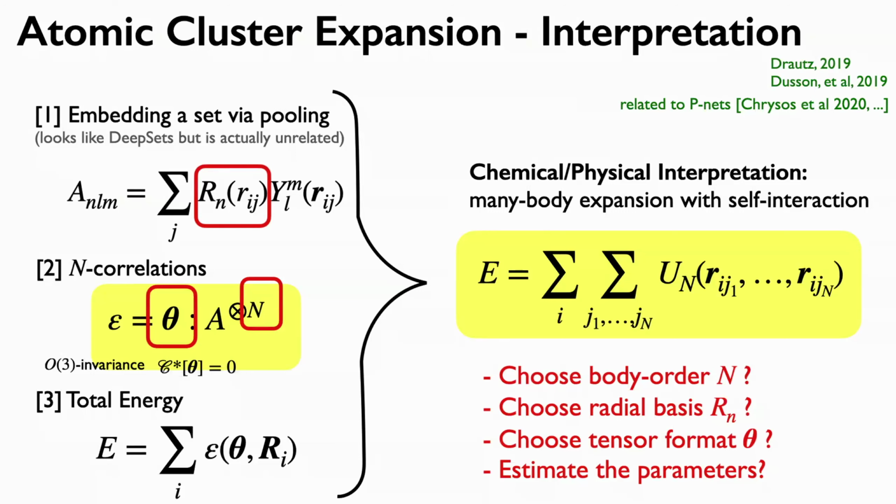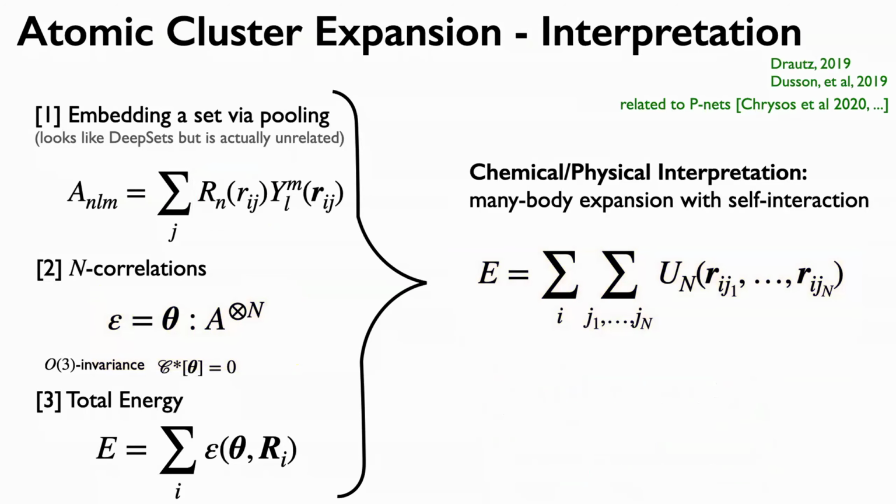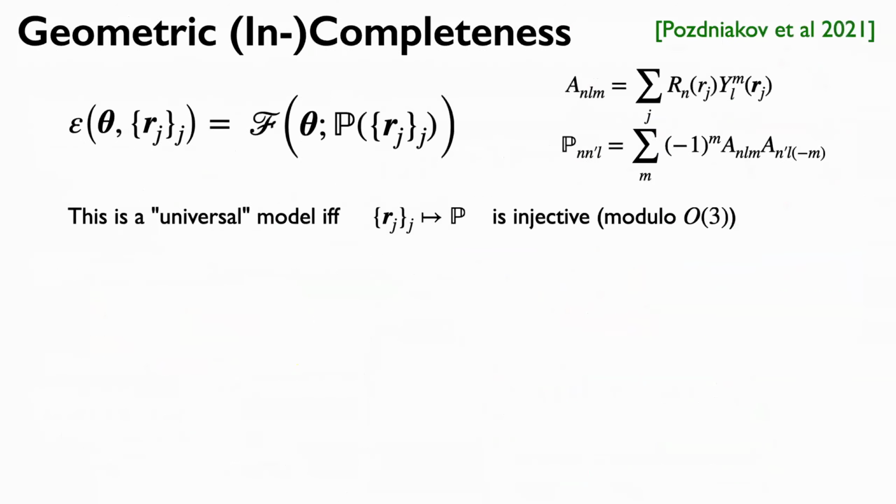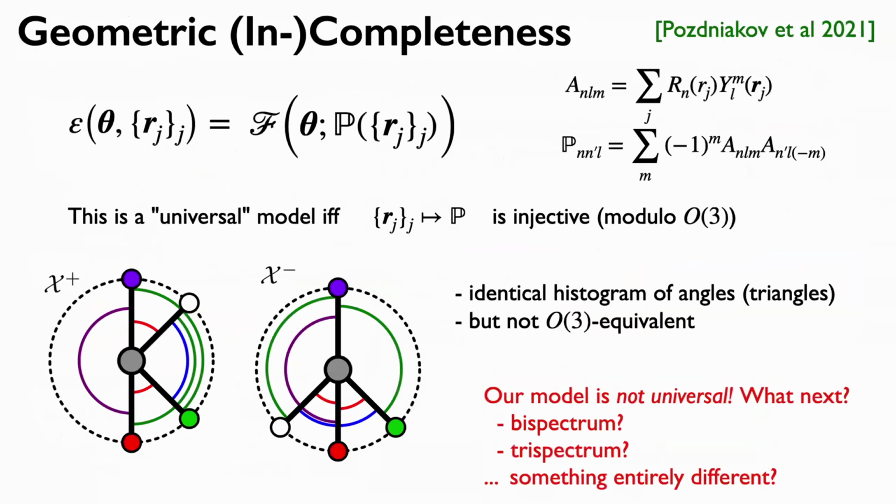Can I add one more thing? You showed some examples earlier of configurations of atoms that are actually quite chemically different, but yield the same descriptor when you extend only to low order. The older, original machine learning potentials use low order descriptors and typically put them into a nonlinear model.